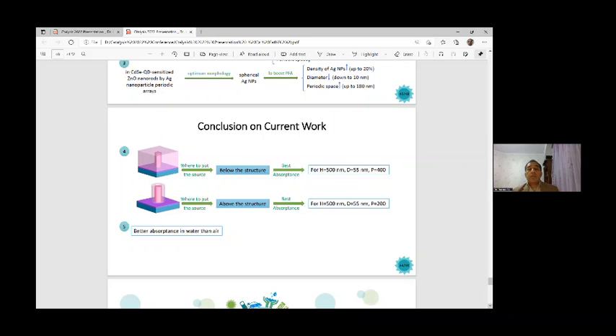but for structure 2, the best absorption and performance will be achieved for a height equal to 500 nanometers, a diameter equal to 55 nanometers, and a center to center spacing between cells in the periodic array structure equal to 200 nanometers. And also, as I mentioned, better absorption and performance will be achieved with a surrounding environment of water rather than air. Water is better than air.